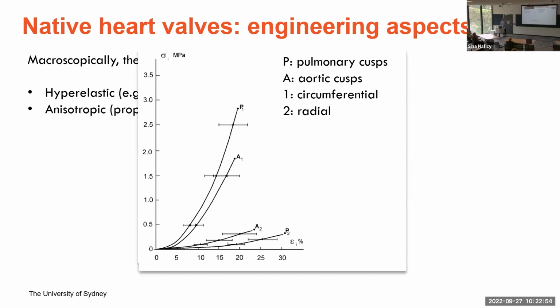If you look at a pulmonary valve or an aortic valve, for instance, you would see that they are very stiff in the circumferential direction, while they are very soft in the radial direction. That means that when they are under pressure, they wouldn't change in size in the circumferential direction. They withstand the pressure, but they can be elongated in the radial direction to seal the valve.